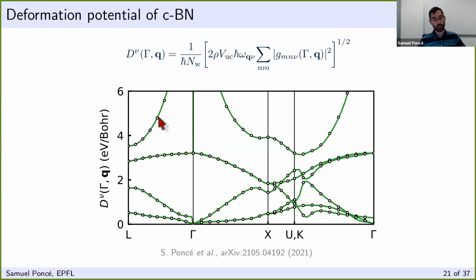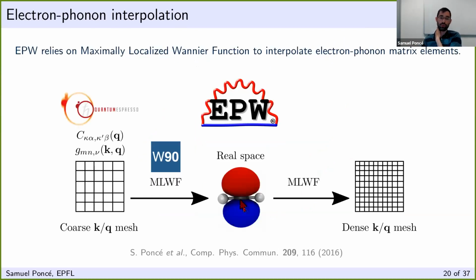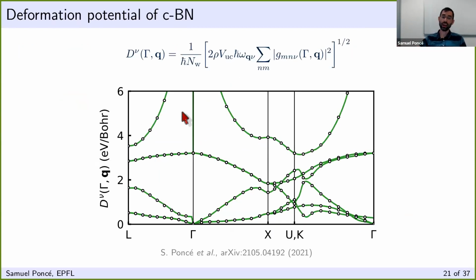As you can see, you have the LO mode, which is diverging as 1 over Q as you approach Q equal gamma, so in the long wavelength limit. And of course, when you do this Fourier interpolation, which was also introduced by Fröhlich yesterday, the problem is that in order to do an accurate Fourier interpolation, you need something that is very localized in space. By definition, those long range effects will not be localized in space. They will be very long range. Therefore, the strategy is to remove the long range, then do the Fourier interpolation, and then add it back at the end analytically.